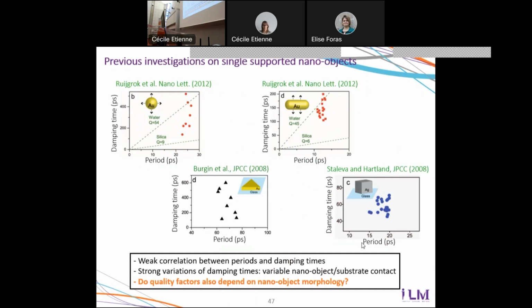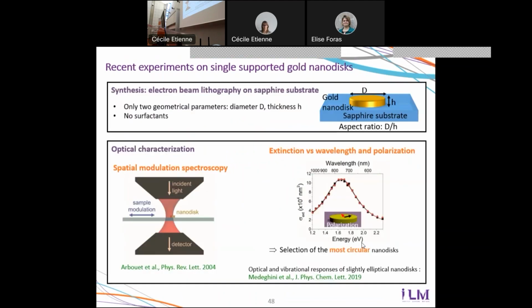Recently, we wanted to see whether these vibrational quality factors actually depend on the morphology of the particle. So to do this, you need to synthesize nanoparticles with not exactly the same shape. So we did that by considering gold nanodiscs produced by electron beam lithography on a solid substrate.